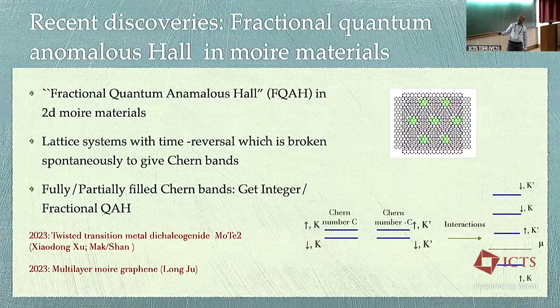Now, if with interactions you polarize the valley degree of freedom and perhaps the spin, if it's also there, then you may end up, let's say with one electron per unit cell, with a situation where there's an interaction generated splitting of these four bands so that only one of these four bands is occupied. Then you have an imbalanced Chern number, and the system is then a Chern insulator and has an integer quantum Hall effect at zero field, right? And this has been seen in many experiments by now in the last few years. This integer quantum anomalous Hall effect in Moiré materials through precisely this mechanism.